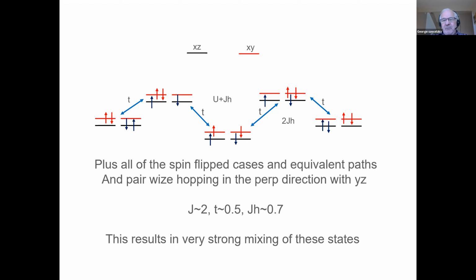But I really feel that because of these degeneracies, you're going to have a Jahn-Teller problem. And I think that because of that, it will want to do something. The one thing it could do is indeed orbitally order and give you the nematic type of phase, as far as the lattice is concerned. And it could even do that before it does the magnetism, because it's so strongly coupled to the lattice. And this picture, by the way, would be an electron-phonon coupling, where the coupling is in the hopping integral, not in the on-site energy.